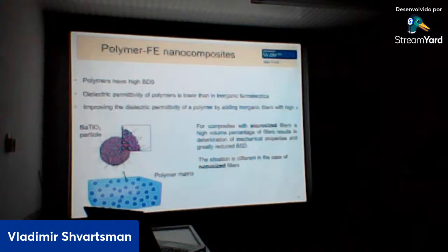So how can we improve these properties further? We can combine polymers and ferroelectric ceramics. Polymers have high breakdown strengths, but they have low dielectric permittivity as compared to the ferroelectric ceramics. So we can combine them. We can make a composite which consists of polymer matrix and ceramic particles, and even better when we use not just large particles, but nanoparticles. In that case, we will have material with large dielectric permittivity, larger than the pure polymer, and better breakdown strength than pure ceramic. So we will take advantage of both kinds of materials.